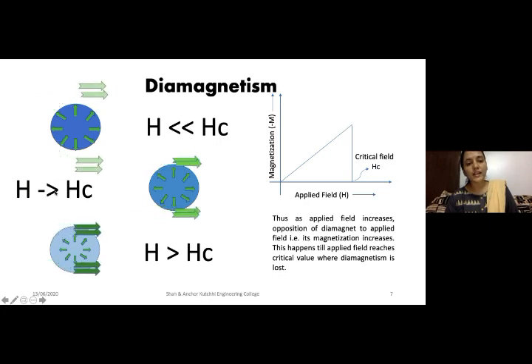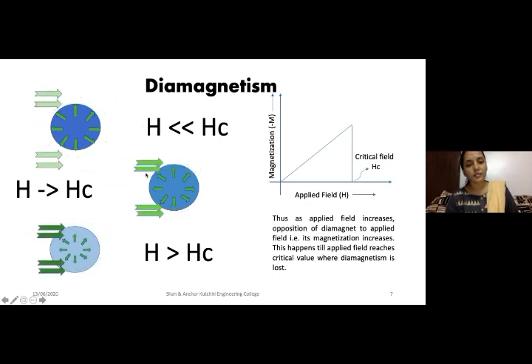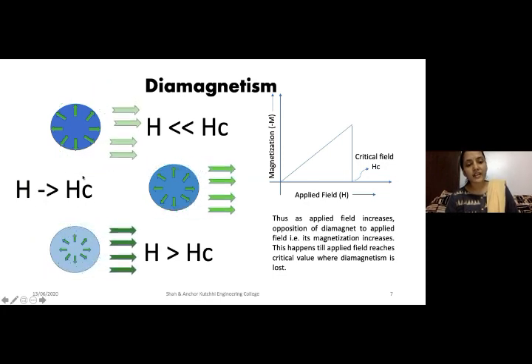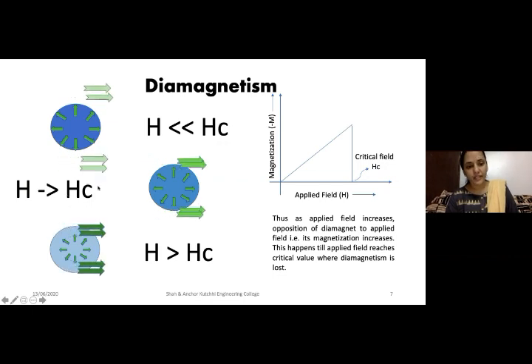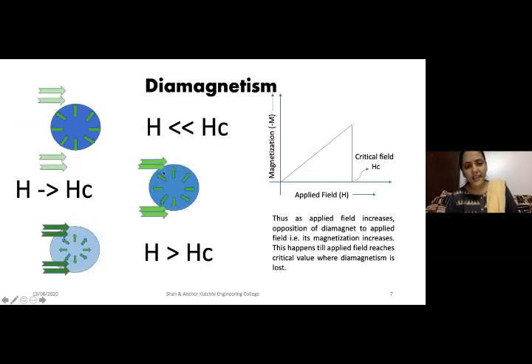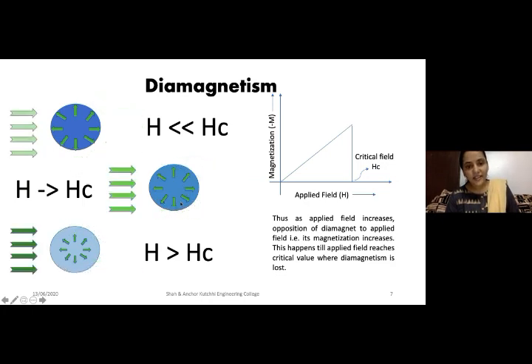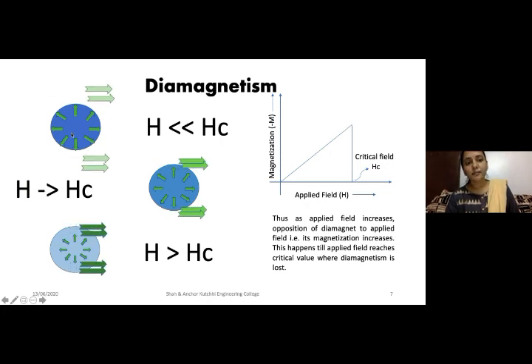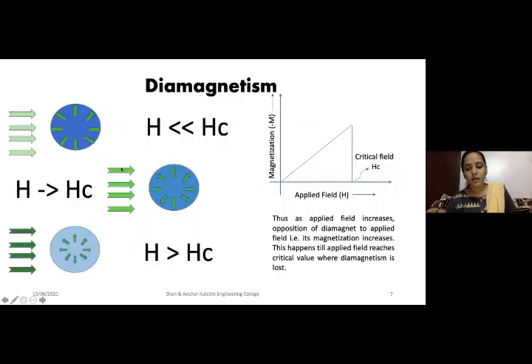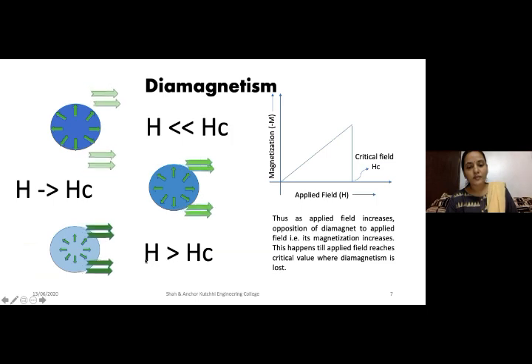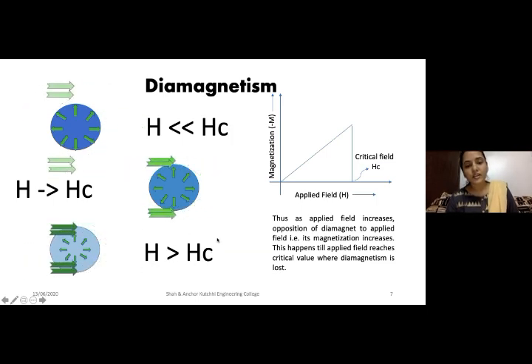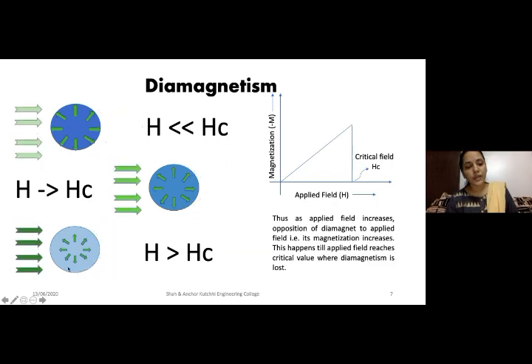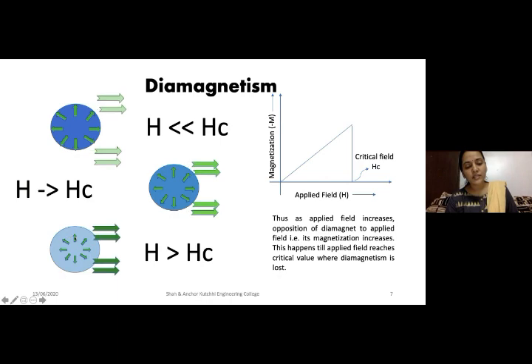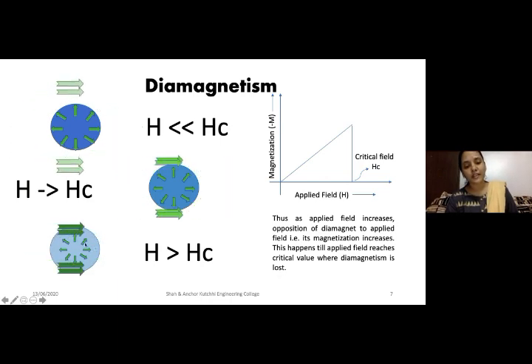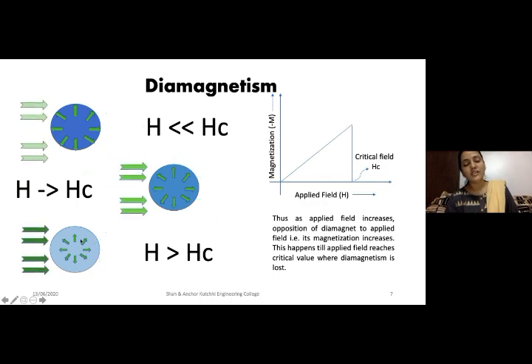But we see as the field becomes stronger, you can see that the green color becoming darker. As the field approaches this critical value, which will be specific for a particular material, we can see that the flux grazes through the material and the internal repulsion of the material is a little weaker. So we'll see that the flux is grazing. Now if we go to the third category, wherein we have crossed the critical field value, at that point of time you can see that the flux is stronger and now the flux can penetrate the body of the diamagnetic material because its internal repulsion is weaker.